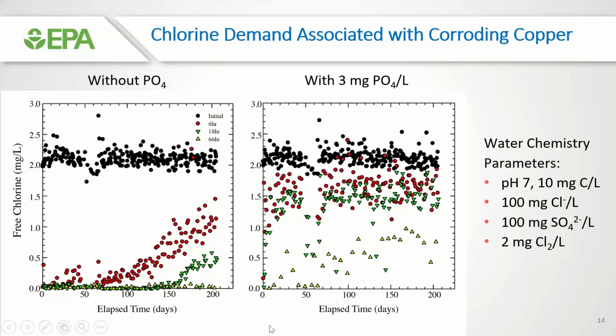People are always saying, well, you add orthophosphate, you're feeding the bacteria, and you're going to increase your biofilm. And I always say, but when you have good corrosion control, particularly in a building where copper plumbing is used and you're adding orthophosphate, this really helps you maintain the chlorine residual. So what's better, no chlorine residual or adding orthophosphate to reduce the corrosion, or the interaction between the chlorine residual and the pipe? Because that's basically what you're doing here, you're interfering with the oxidation of the pipe wall, the metal portion of that, because the orthophosphate's there for good corrosion control. So really, really important point.